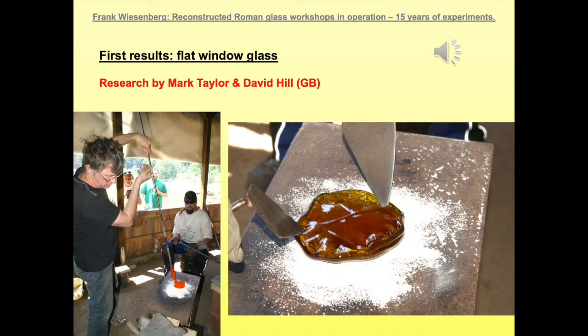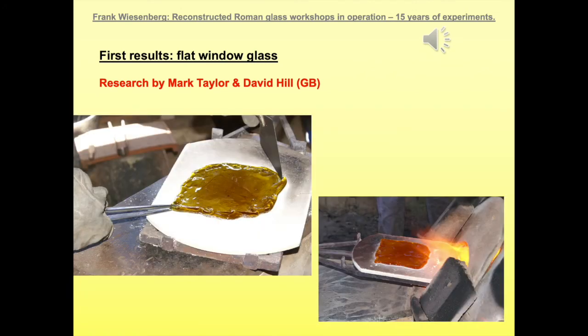Next idea, which was tested during the glass furnace project, was making of window glass, starting with flat window glass, which is often quoted as being cast window glass. Well, Mark Taylor and David Hill have another suggestion. They take a portion of hot glass and take it to a solid support with some separator on top of it. They pull it to a disc. The flat disc is then pulled into a rectangular or square shape using pincers and trowels.